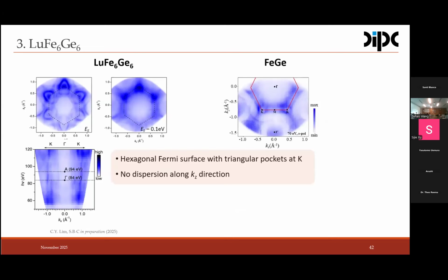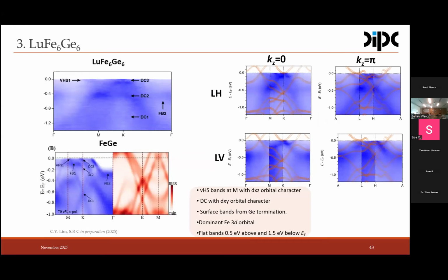And then if we look at the ARPES spectrum, here I plot the Fermi surface map, which actually looks hexagonal, a bit different from iron germanium, but still we have a hexagonal Fermi surface with pockets at the K position and some electron pocket here. The compound is essentially two-dimensional. We don't see any dispersion or barely any dispersion of the bands. Perhaps this disperses a bit, but it's merely a two-dimensional Fermi surface. If we look at the valence band, we can distinguish the Van Hove singularities at M, some Dirac crossings at K. Bands are a bit broader compared with iron germanium.